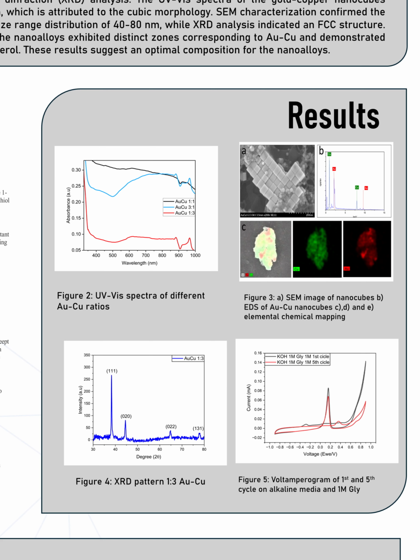The X-ray diffraction pattern displays diffraction peaks of the 1 to 3 gold-copper system. The peaks of the 1,1,1, 2,0,0, 2,2,0, and 3,1,1 planes can be seen at 2 theta degrees of 38, 44, 64, and 77 degrees respectively.